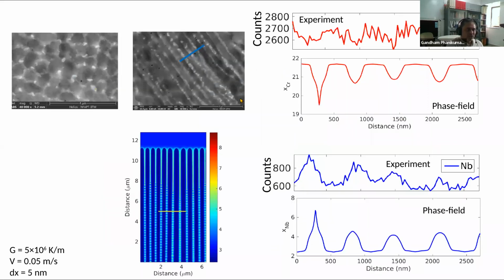Okay. Now we also benchmark these simulations. So here is an experimental specimen. The tracks are here, the laser tracks, the cellular patterns of the laser track is here. So when you take a line and then do the compositional analysis, you see ups and downs of the composition like chromium content or niobium content. And the simulation is shown here in bottom figures, showing you that we can reproduce those ups and downs of the compositions quite well in terms of the wavelength of the composition variation as well as the amplitude of the composition variation. If you calibrate it for one sample, you can reproduce it for many samples.